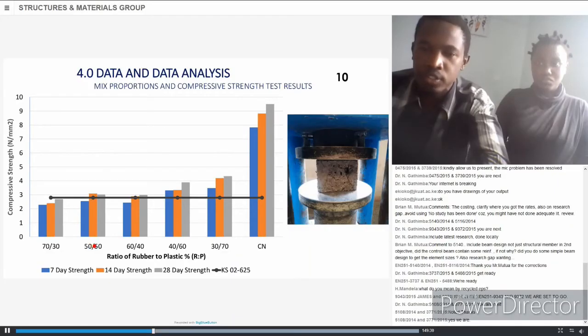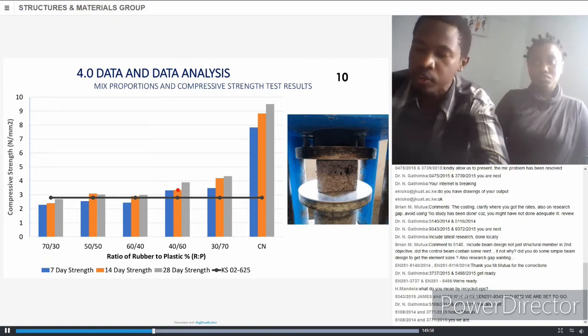So we did mix design and varied the ratios of rubber to plastic, and the highest compressive strength was obtained with the mix that had 30% rubber and 70% plastic. And also the 40-60% rubber to plastic ratio met the threshold provided by the Kenya Standard KS 02-625/1983, which sets a minimum of 2.8 newtons per millimeter squared for non-load bearing blocks.